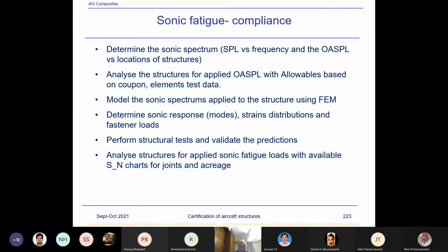Sonic fatigue compliance: determine the sonic spectrum, SPL versus frequency, and OSPL versus locations of the structures for various structure locations. Analyze the structure for applied OSPL, overall sound pressure level, with allowables based on coupon element test data. Model the sonic spectrums applied to the structure using FEM. Determine sonic response, strain distributions, and fastener loads. Perform a structural test and validate the predictions. Analyze the structure for applied sonic fatigue loads with available SN charts for joints and acreage.